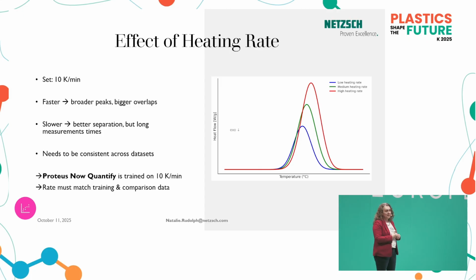The next is effect of heating rate, also messes things up. You see here also in the schematic, low heating rate in blue, high heating rate in red. Again, it's a DSC of one and the same material, but depending on what parameters you use for the measurement, your curve will be very different. And I think those of you who work with machine learning probably already think about, okay, if you have such varied data, how do you train a model? Because of that, we defined mass and heating rate for all of our training data, that's set. And that also means the rate and mass must match of whatever we want to analyze. That's the conclusion out of that.